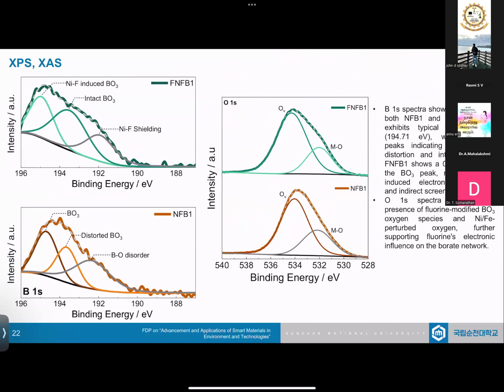So moving further, we can see that the BO3, the boron B1S, is also being slightly altered because of the fluorine being attached to the system. And one good thing is that the BO3 framework is still stable. It is distorted when you bring in fluorine, but it's still stable. That means that the framework is still withstanding, and that might be a good thing for your applications.